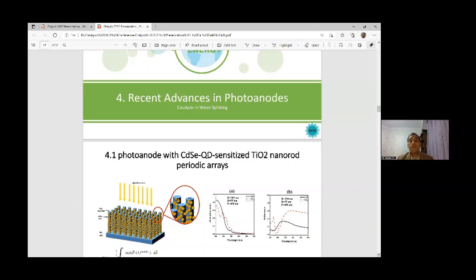We usually utilize quantum dots for increasing the surface to volume ratio, so as to increase the absorption of sunlight. Here you can see this advantage and this goal. Here you can see the photoanode structure is a periodic array of titanium oxide nanorods sensitized by quantum dots of cadmium selenide. Typically, I can say that titanium oxide and zinc oxide are two important candidates for this purpose. One-dimensional metal oxide semiconductors have gained much popularity over the past decades due to their availability, stability against sunlight, and non-toxicity, and have attracted researchers during the past years.